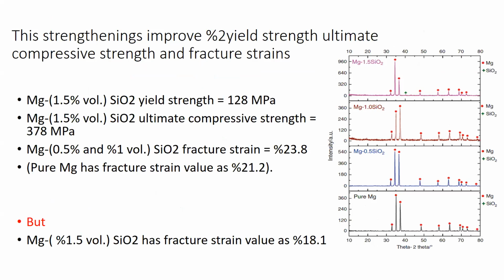However, adding particles at more than 1% volume causes agglomerations which act as stress raisers, and this decreases the fracture strain. As we can see on the X-ray diffraction, basal plane intensity peaks at 1.5% volume silicon dioxide.